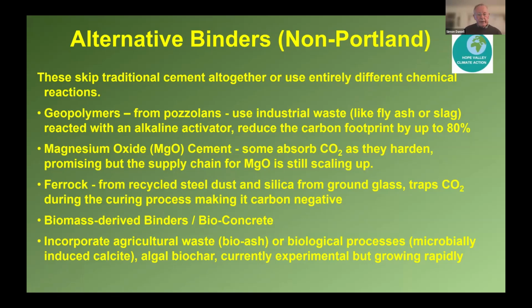Ferrock from recycled steel dust and silica from ground glass, they trap the CO2 during the curing process. So they can become carbon negative ways of producing concrete. There are biomass derived binders to make a bioconcrete, and you can also put in agricultural waste, bioash, algal char. These are very experimental. This is a very complex, rapidly developing area, and I find it quite hard to really do it justice. But I'm hoping that I'm giving you a flavour for what's going on to try and decarbonize the